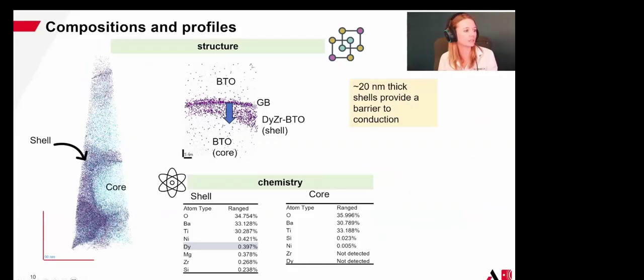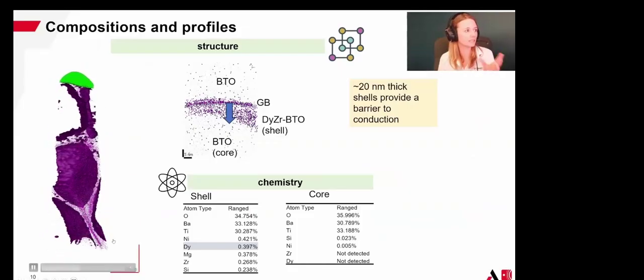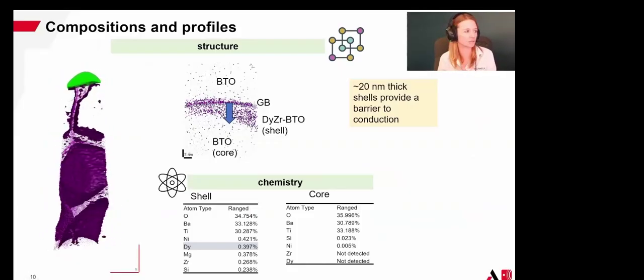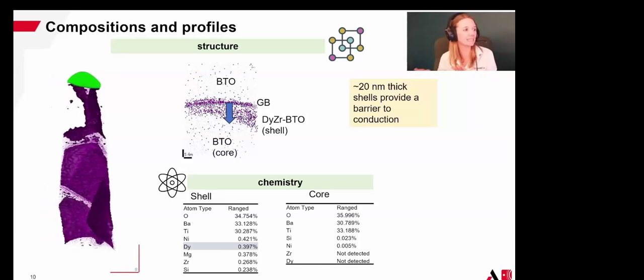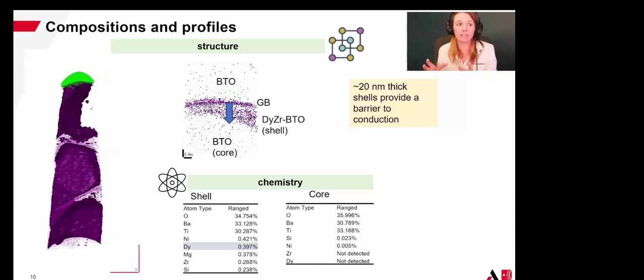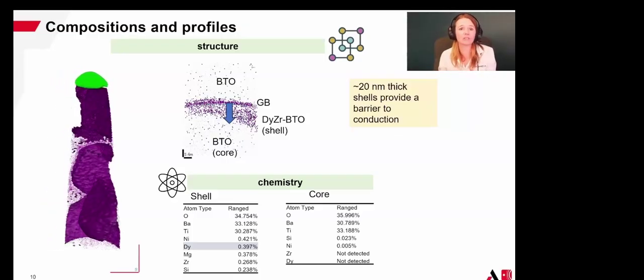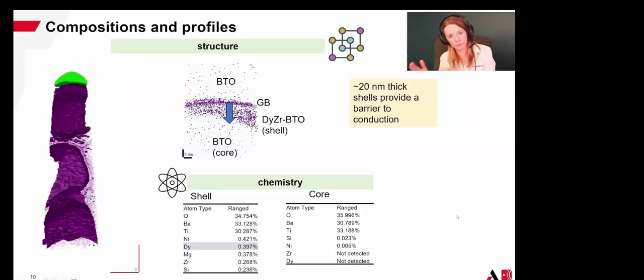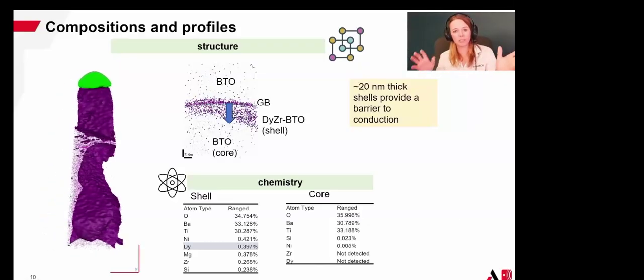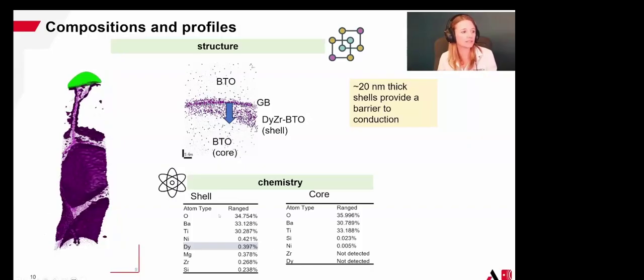Now we can look at that a little bit more closely in 3 dimensions. Here we have an isosurface of dysprosium, zirconium, and nickel, which is highlighting these regions where we can kind of define a core. Now that's going to allow us to look at the bulk composition within these cores and compare them to the shell regions. And what we find here is that our shell is pretty heavily enriched, a little bit less than 0.5% in dysprosium, whereas as we go to the core regime in our bulk composition, we're really not detecting any of those special dopant atoms such as zirconium and dysprosium.